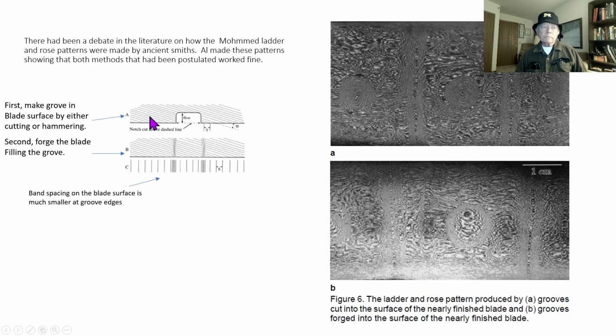Now, here's a picture that shows the aligned bands you're starting with. I want you to notice that they're at an angle to the surface, so that on the surface there's a distinct spacing as long as the band spacing remains constant. Now, what you do after you make the cut, the cut's not very deep, and you forge it flat. Now think about what happens to those bands. They have to rotate. This band has to line up with that one.